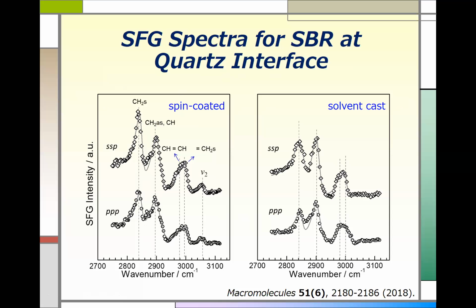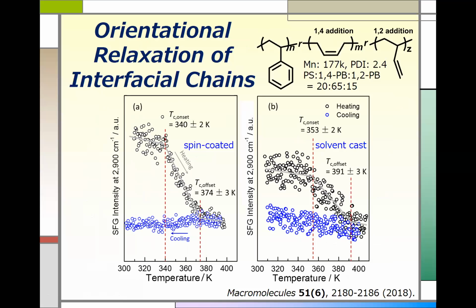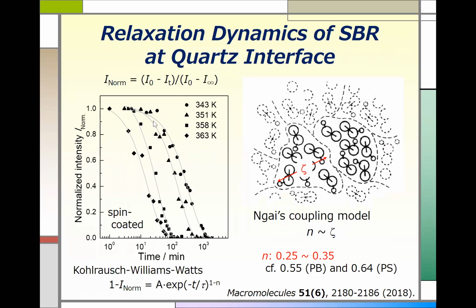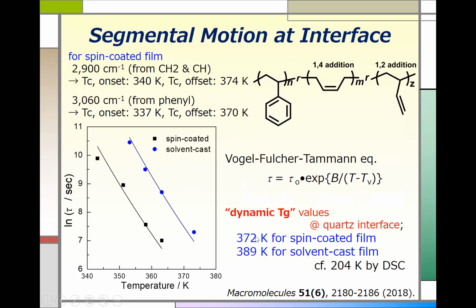So we again applied some sum frequency generation spectroscopy, and we take a look at the relaxation behavior of polymer chains, and we applied fundamental polymer analysis using KWW relaxation and the Vogel-Fulcher equation and so forth. Then we are able to determine the glass transition temperature of polymers directly attached to solid materials. So this is just an example. And the Tg of SBR by DSC was 204 K, but SBR chains on quartz, the Tg is going to be extremely high, approximately 200 Kelvin higher than the bulk.